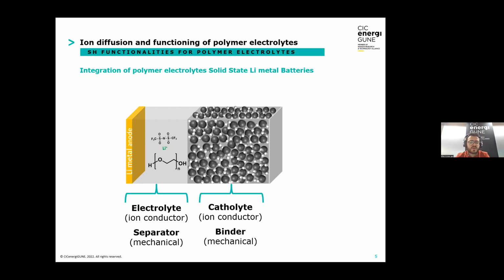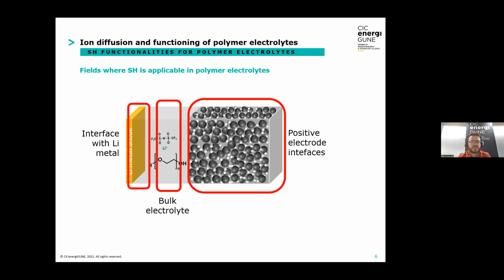There are actually three different regions that we've identified where polymer electrolyte can have self-healing functionalities with different types of functions, which would be the interface with the lithium metal negative electrode, the bulk electrolyte, and the positive electrode with the active material interfaces and the interfaces with the electronic conductor, the carbon additives. So there is a wide range of applications for which a polymer electrolyte can be functionalized with self-healing functionalities that can be solved.